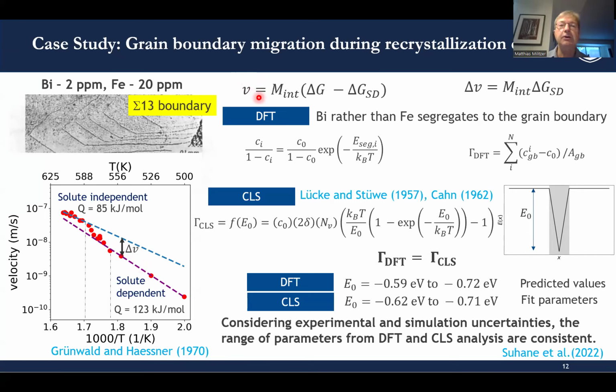If you look at the velocity of the boundary, it's the boundary mobility times the effective driving pressure, which is in this particular case the driving pressure of recrystallization due to the stored dislocation density. And that's reduced by a solute drag pressure. Now, what we can do with DFT, we can calculate what the binding energies of bismuth and iron at the boundary will be. We found that it's bismuth that segregates rather than iron. We calculated the binding energies for each individual site at the boundary, and then estimated the probability of occupancy of these individual sites at the temperatures of interest where the recrystallization takes place. And we can, out of this, determine, based on the DFT simulations, what we expect as enrichment of bismuth at the interface, basically in atoms per square nanometer.